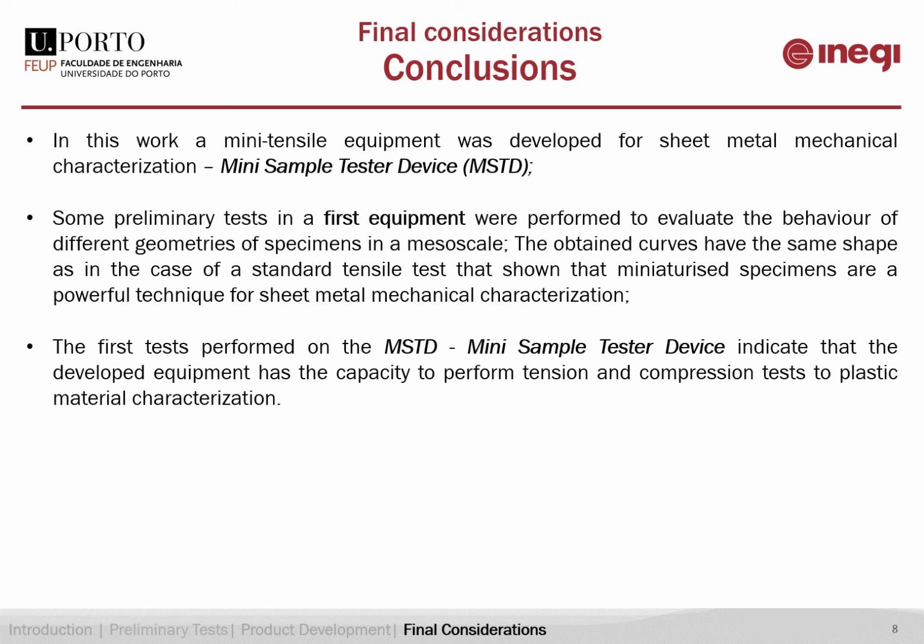The obtained curves have the same shape as in the case of a standard tensile test, thus showing that miniaturized specimens are a powerful technique for sheet metal mechanical characterization. The utility of the DIC technique for mesoscale tests was also confirmed.